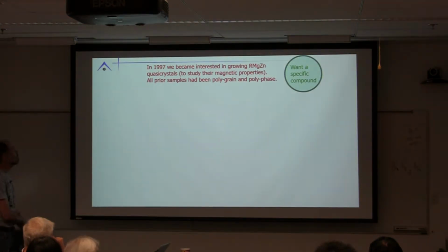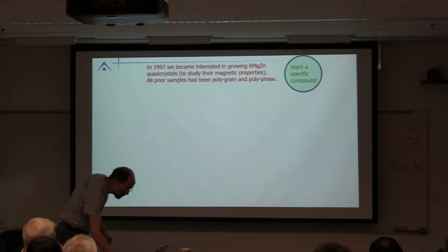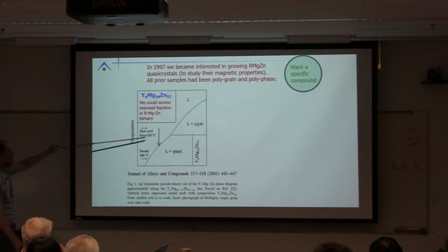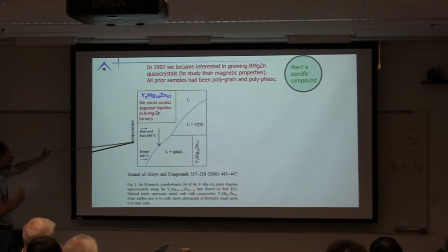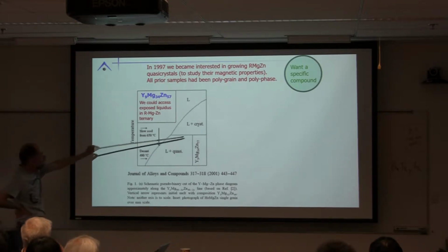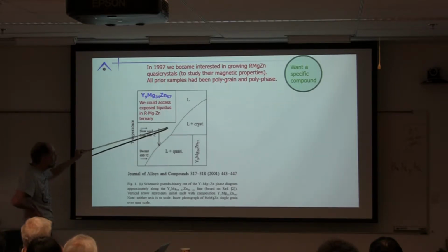In '97, we were interested in growing rare earth magnesium zinc quasicrystals. Okay? Basically, we wanted to study their magnetic properties, but as a first step, we needed to make single phase, single grain, because all prior samples had been polygrain and polyphase, and that led to difficulties. Okay? So, here's the phase diagram we ultimately were able to establish. Basically, we have a quasicrystalline phase that we can grow out of excess magnesium and zinc.